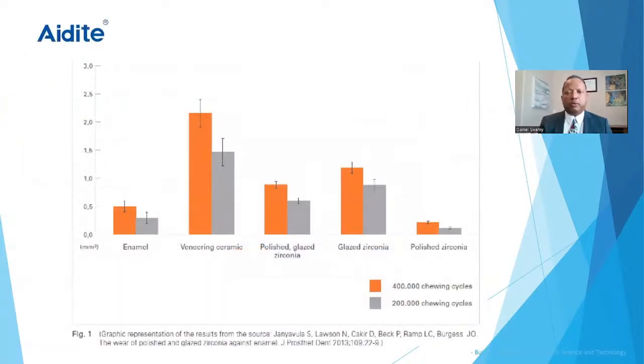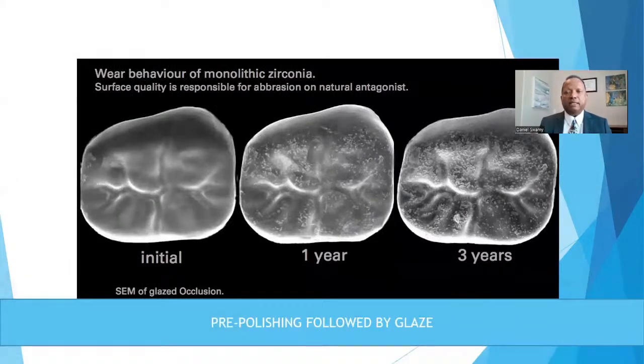So one of the things that we did at my previous workplace, we actually started to test how enamel works against natural dentition, and how zirconia restoration works against natural dentition. A pre-polished zirconia restoration is very good in the sense that it does work like normal enamel. During the mastication process, as well as the various cycles that it goes through, you actually do get a very nice surface.